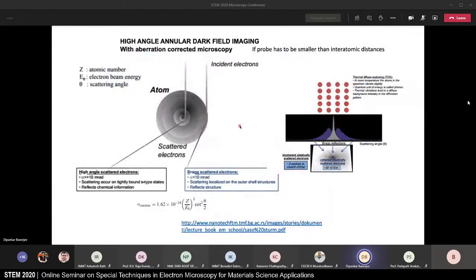A second technique is to use high-angle annular dark field imaging. And what this does is to use elastic scattering by the innermost electron cloud and image that elastic scattering process through higher angles. Something like 10 milliradians is the limit of Bragg scattered electrons. You're looking at high angle scattered electrons to the extent of something greater than 10 milliradians.